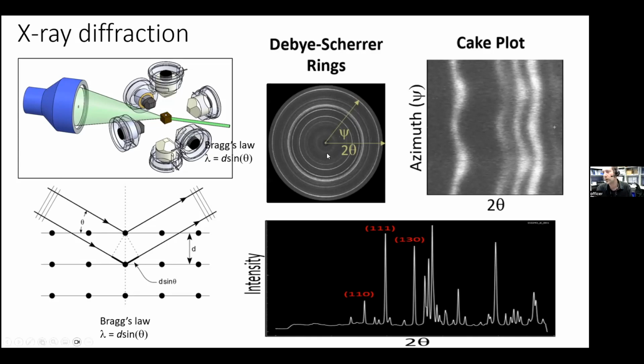And this is just showing if we plot the radius, which is 2 theta, versus the azimuth, so it's like we're unwrapping these things. If it was hydrostatic, these would just be straight lines, but they become these sort of sine squared things. And then we can plot this and measure the deviatoric stress and the pressure. We can also integrate around these rings to get a regular diffraction pattern.